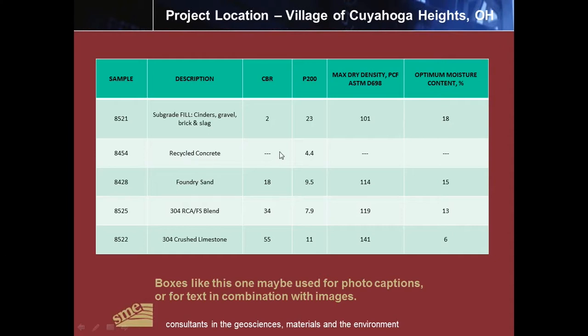We didn't run a lot of other tests on the recycled concrete other than an initial gradation and a fines content, so that we could take the recycled concrete and break it into different constituents and blend it with the foundry sand. Our foundry sand material had a CBR value of 18, and 9.5% passing the 200 sieve. Typically with foundry sands in our area, this number is usually around 2 to 3%, but the source we were using for this project was slightly higher.